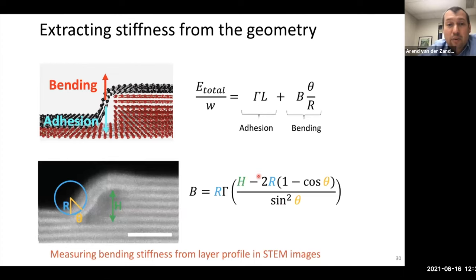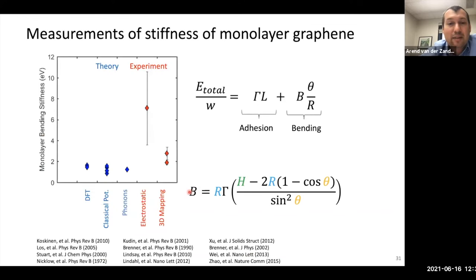So now what we do is we look at the bending and adhesion energies, and we build a little equation that says that by considering these two factors, we can extract the bending stiffness by just looking at the shape of the bend. We look at the radius of curvature of the bend and how much it's bending by and the height of the step, and thereby we can extract this bending stiffness.